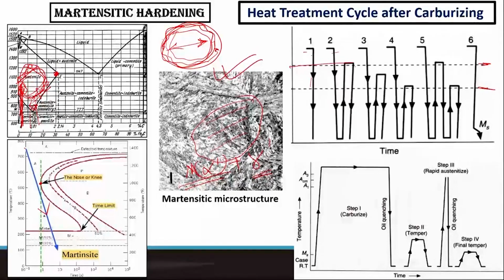Now, after we have carburized, particularly let's say a pack carburized component, this is carbon enriched all right, but not yet martensite. So how do I arrive at this martensitic surface or martensite enriched surface? Then I again have to reheat the surface and then quench. But if I do that, then this is going to create again a situation where I am subjecting the component to higher thermal shock, and also possibly something that I don't need, because the core is at a lower carbon content. And for 0.2%, if you want to go to austenite and quench, you may end up getting martensite, but that martensite will have very low carbon content and is inadequate to give me any wear resistance. And that's not desired either.